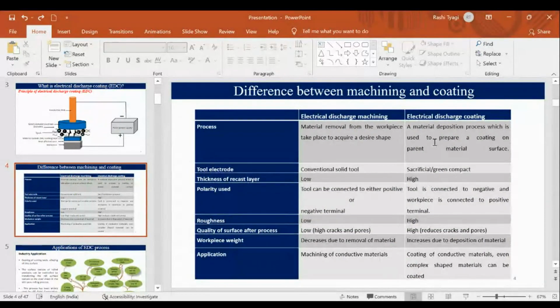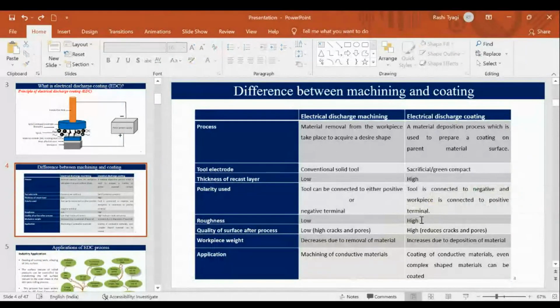The roughness we get is high in the EDC process, because it's natural that when the material gets deposited, many peak and valley heights form. There will be a protrusion type of structure, so the roughness becomes high. That is also one of the limitations of the EDC process. So we can do post processing to improve that. Then the quality of the surface is high, with fewer cracks formed.